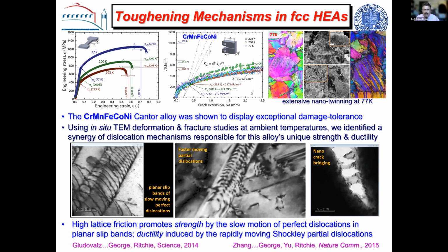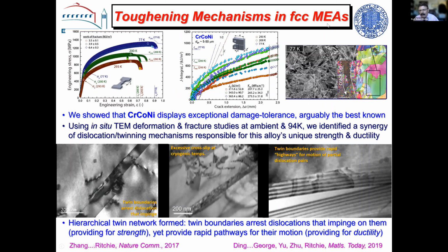Now we looked at a separate one, a simpler one. We called this a medium entropy alloy, and this is just chromium, cobalt, nickel. We've left the manganese and the iron out. This is a stronger material, and now this is the tensile test at room temperature, 200 Kelvin and 77 Kelvin. We're up around 1.3 gigapascals.